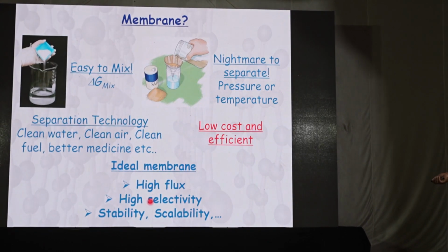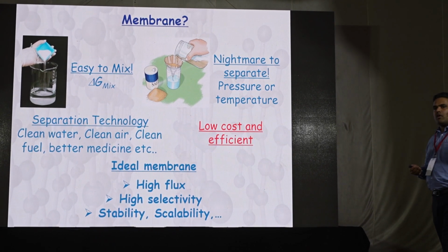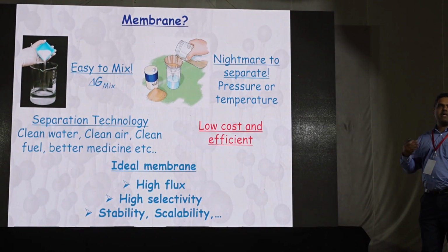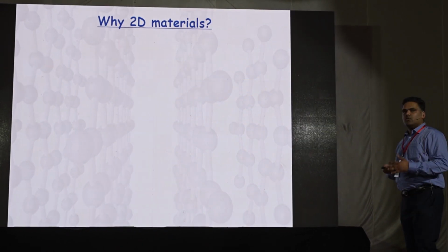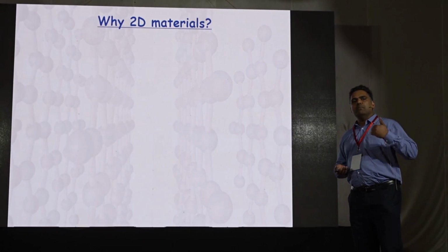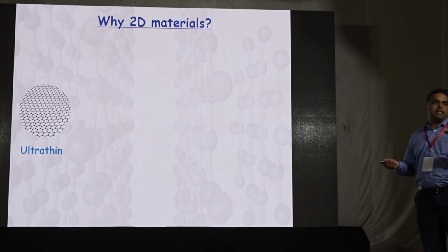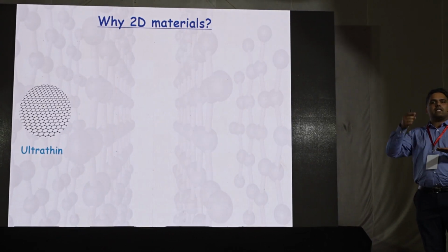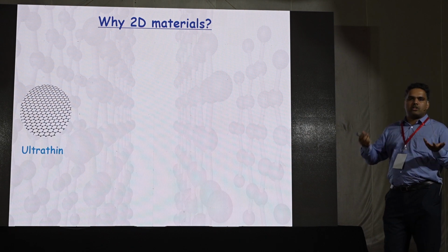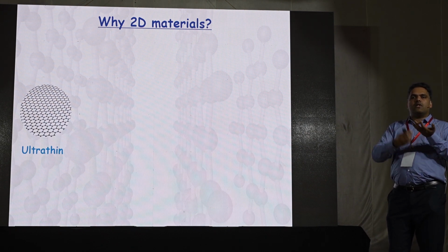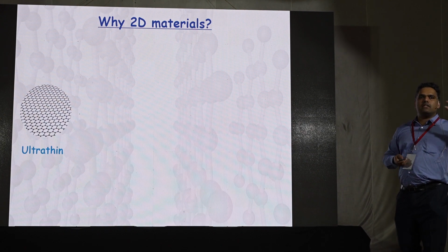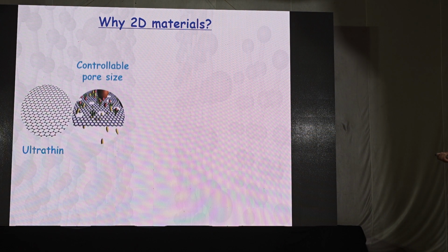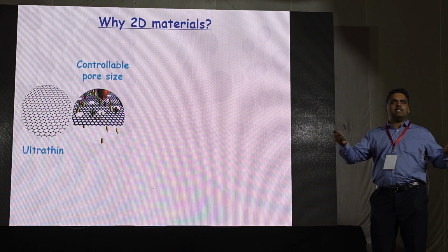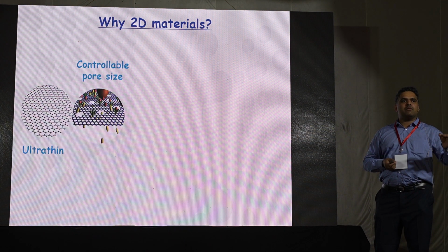High selectivity means it should be able to selectively pass one species with respect to the other one. And that membrane should be scalable. And that is why graphene or any 2D material-based materials are now important for membranes: because they are very thin, ultra thin. Ultra thin means the transport resistance across the membrane will be very low. For molecules to pass from one side to the other, the time required is very short because it is super thin. Another reason is we can tune this membrane to make any pore size we want. You can drill holes of whatever size, you can have a 1 atom hole or 2 atom or 3 atom, whatever you want.